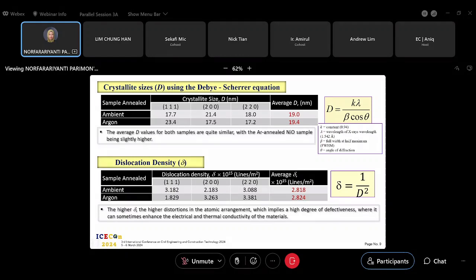The higher the dislocation density, the higher the distortion in the atomic arrangement, which can imply a high degree of defectiveness. The defectiveness can be positive or negative, but in terms of positive, it can sometimes enhance the electrical and thermal conductivity of the material. As I said earlier, we have to improve the characterization with others, let's say the electrical measurement, to know which is better from the results.